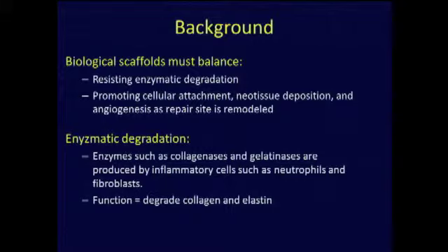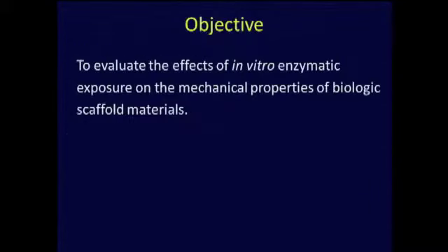This process of remodeling is really a balance between the resistance of it being enzymatically degraded during the same process of promoting the tissue remodeling with cellular attachment, neotissue deposition, angiogenesis. So this process of remodeling is a balance between those two processes. An imbalance, one way or the other, may alter the actual integrity of the healing site. Enzymatic degradation is done through collagenases and gelatinases, or MMPs, that are produced by both inflammatory cells and fibroblasts. Again, this function is to degrade the extracellular matrix and allow remodeling to occur in the healing site.